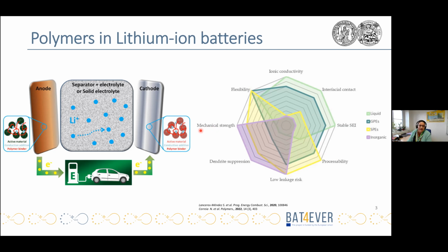In general, it can be stated that the polymer electrolytes are significantly increasing the mechanical integrity and the thermal stability of the electrolytes, however, at the cost of the ion conductivity. So they are having in general less ion conductivity compared to the conventional liquid electrolytes used nowadays in the batteries.